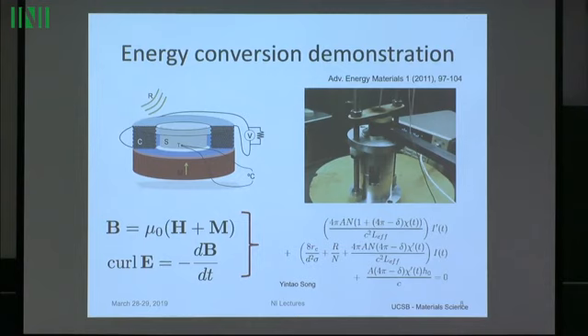So anyway, it's the dipolar relation and Faraday's law that we'll use, first in a very qualitative way, to try to analyze what happens in this energy conversion device. So first of all, as you go through the phase transformation, biased by this permanent magnet, the magnetization, remember, is a vector field on this configuration. The magnetization should increase suddenly. In fact, it should go up to quite a large value. That means dM/dt is very large at some level, or some average of dM/dt is very large. And you can see from this relation, dM/dt is partitioned between dB/dt and dH/dt.